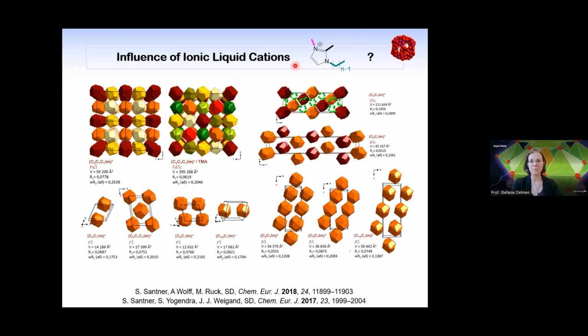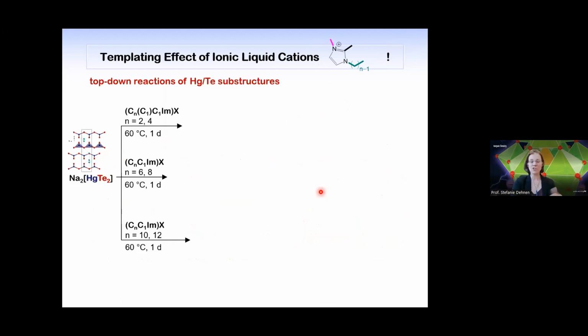So this ball type, the zeo ball, how we call it, the anion, does not change. It's just the packing mode that changes. So the ionic liquid cations just control the packing, which was kind of disappointing since we wanted to see an impact, a templating effect of this counter ion, which is so much involved in the structures. But then we had to change the system.